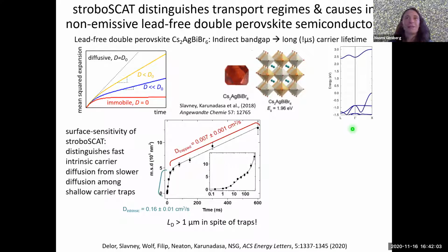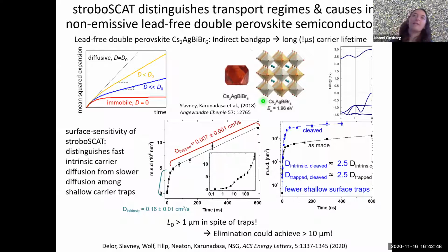Okay, so stroboscat shows multiple temporal regimes. So we hypothesized that bromine vacancies, in this case, were creating shallow charge carrier traps, and that initially the carrier density exceeds the trap density, so that we can essentially demonstrate the intrinsic diffusivity. And that once the traps are no longer saturated, we're observing lower diffusivity because we observe hopping among these traps. Okay, so suspecting that these traps are bromine vacancies that are concentrated at the surface, Milan cleaved one of these beautiful crystals and measured at a fresh surface, and he showed that this enhanced the diffusivity in both of these two regimes. So this is very cool in the sense that already with these traps present, the migration length was greater than a micron. And then if there were a way to get rid of those traps on a more permanent basis, then you could gain another order of magnitude.